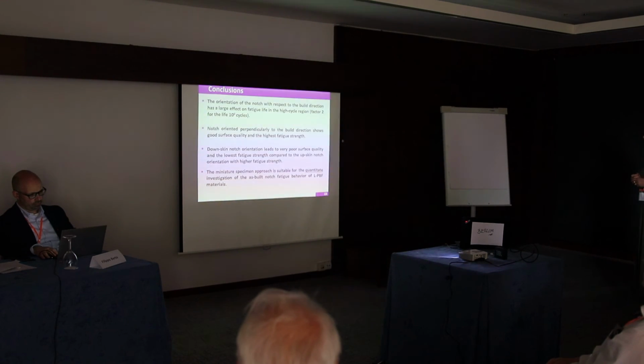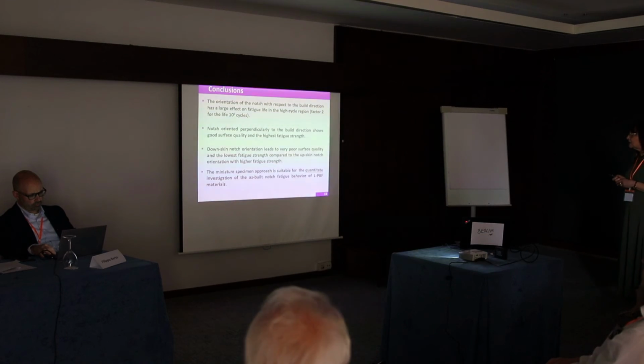The miniature specimen approach is suitable for the quantitative investigation of the as-built notch fatigue behavior of laser powder bed fusion materials.